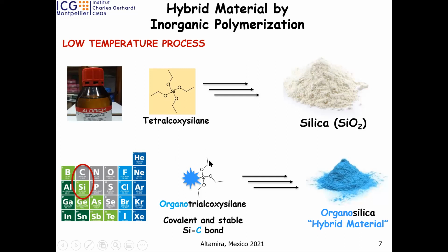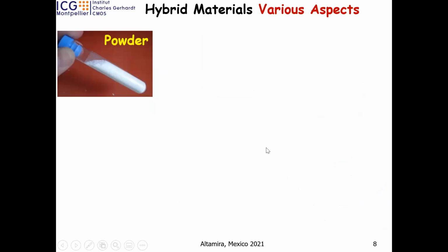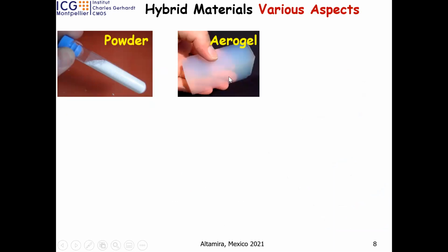And if you functionalize, if you remove one alkoxy group and put in any type of dye, here just a cartoon by this blue star, and you make the same reaction, at the end you obtain organosilica. So you have SiO2, but you also have an organic group on top, which gives this color. By this way, we can prepare materials as powder, as aerogel. If you make drying under supercritical conditions, you obtain aerogel, a very light material with nice properties.